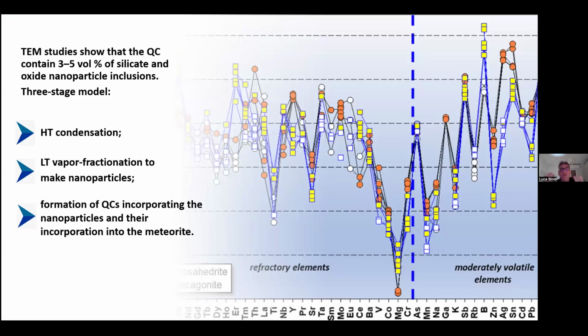All the quasi-crystals then studied by laser ablation were originally studied by transmission electron microscope, and we found that all the quasi-crystals contain nano inclusions, 3-5% by volume. I'm referring to inclusions of oxides and silicates. So the theory, based on the trace element distributions, was that we could have a high temperature condensation at the beginning, then a low temperature vapor fractionation to make the nanoparticles, then the formation of the quasi-crystals incorporating the nanoparticles, and finally the incorporation into the meteorite. It is a multi-stage scenario.